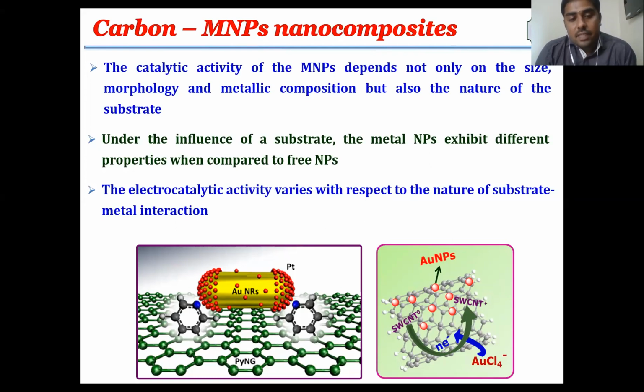The graphene oxide, since it has many functional groups, can act as an anchoring site to incorporate the metal nanoparticles, and the electronic property of the material can be improved by the composite formation. So, carbon nanotubes are another type of carbon material, and the composite of carbon nanotubes and metal nanoparticles gives another property which is superior to the individual one, which is found from the cooperative effect between CNTs and the metal nanoparticles.